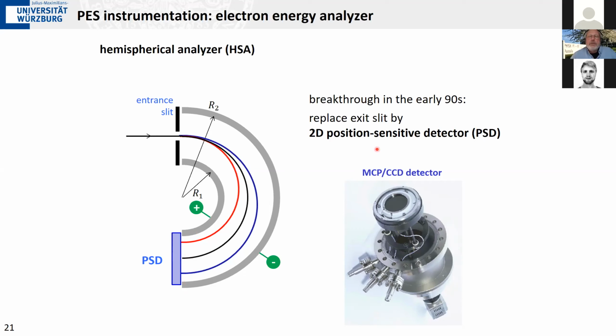What we use here as 2D detector is basically a microchannel plate. So these are very thin glass plates with millions of little holes in them, which act as electron multipliers. You apply a high voltage at them, so they will turn a single photoelectron hitting the entrance side into an electron cloud of 10 to the 6 to 10 to the 8 electrons. And these electrons will then be further accelerated onto a fluorescence screen and be turned into a photon flash, which will be recorded with a CCD camera. That's a typical detector that we have in these analyzers.